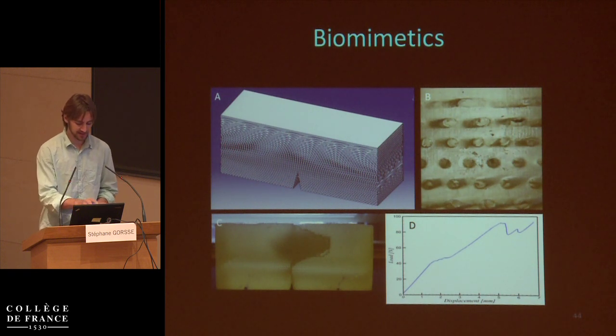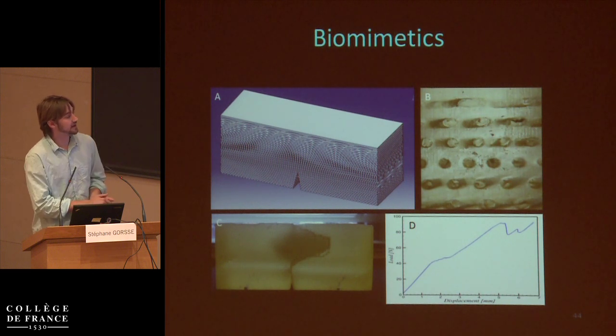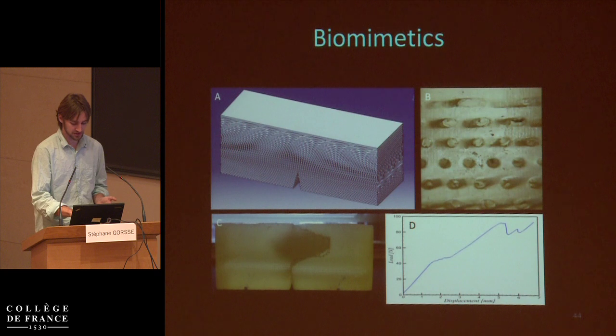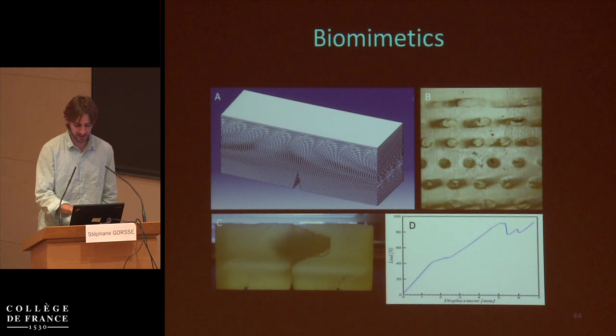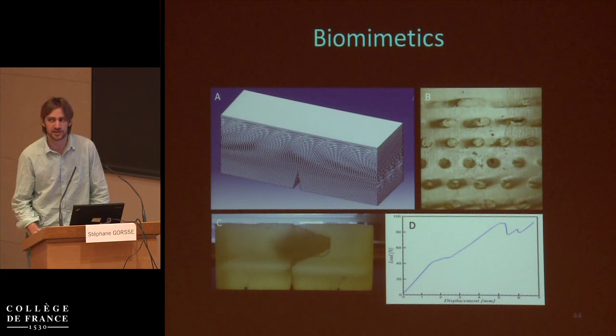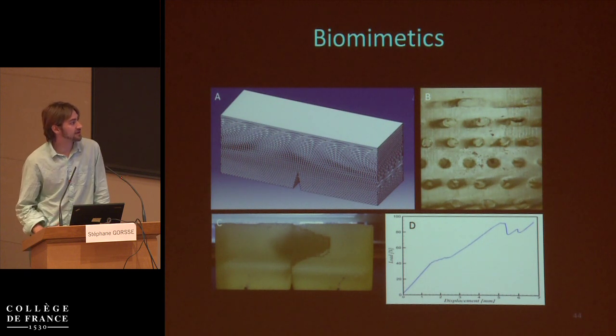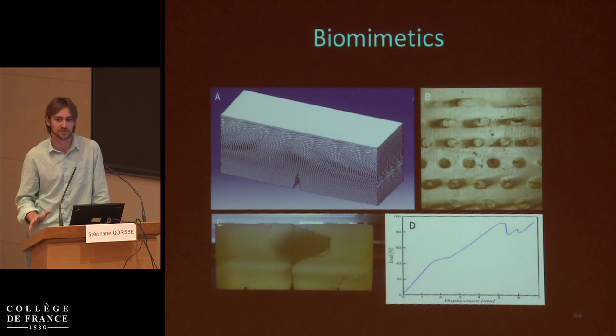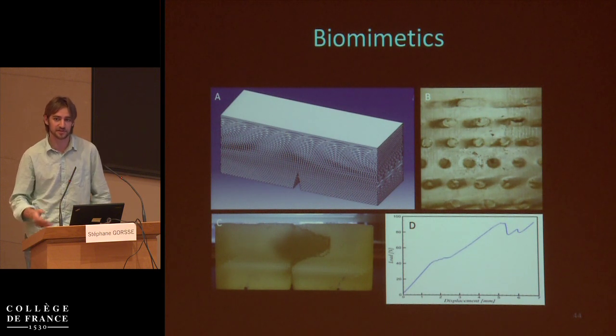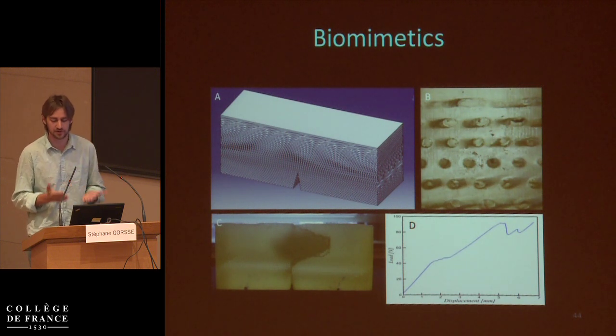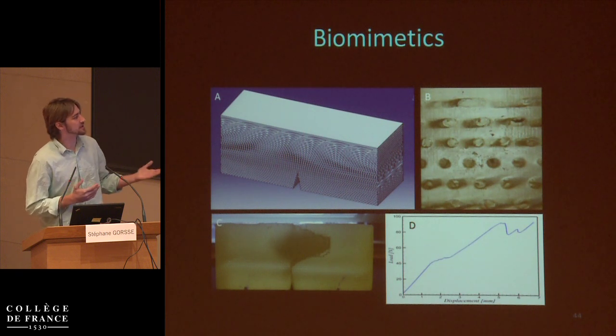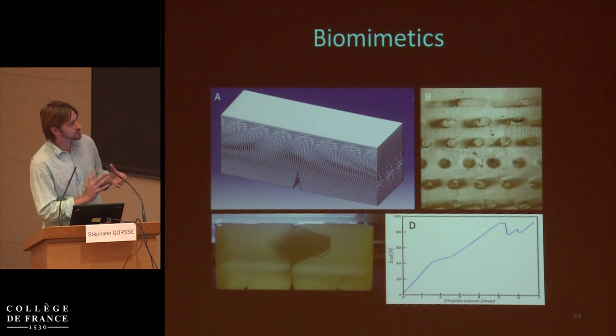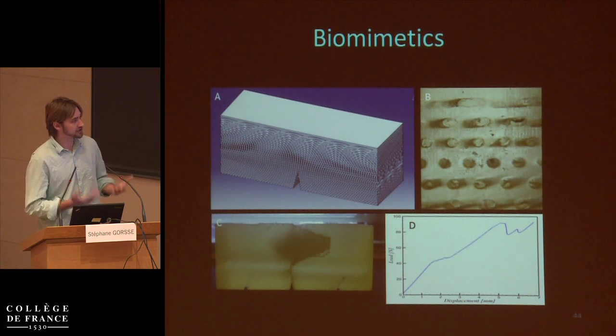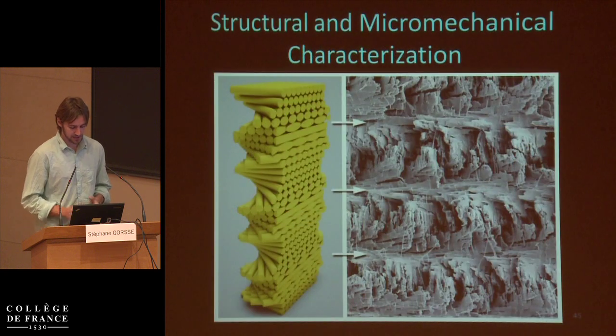And so then we put it into a three-point bend, and you can see that the fracture was in fact rotated. And most importantly, the stress strain curve, or the load displacement curve here, is actually increasing. And this is very strange because typically for a fracture, you will have a decreasing force because it becomes easier to drive a fracture as you create a larger crack opening angle. And so this is the power of a helicoidal composite: by twisting the fracture, you actually increase the driving force for fracture propagation.